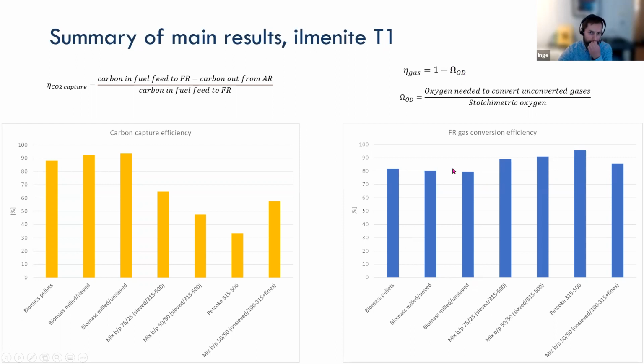So the same experiments then show that for biomass, we are around 80% fuel reactor gas conversion efficiency. And it actually increases the more petcoke we put in, which may seem strange, but it's because less gas is really produced. So a lot of the fuel goes to the air reactor. And then it's an easier task to convert the gas, the little gas that is produced, to CO2 and water vapor.